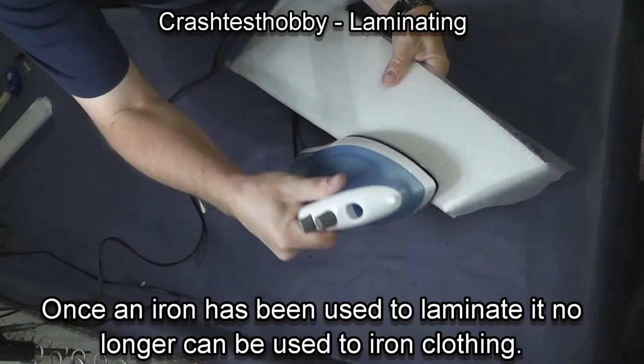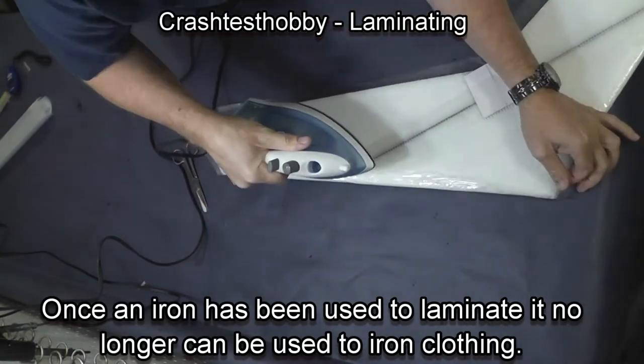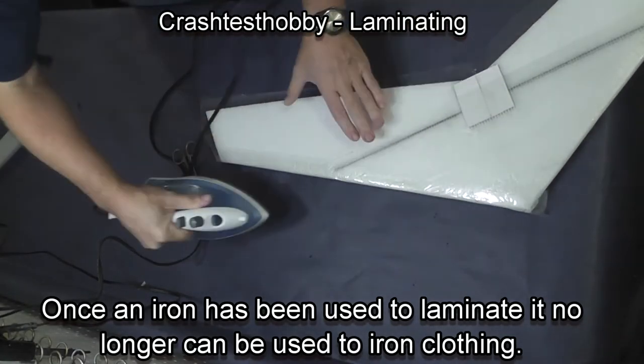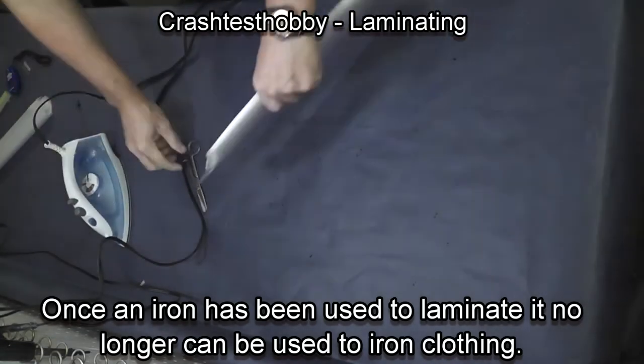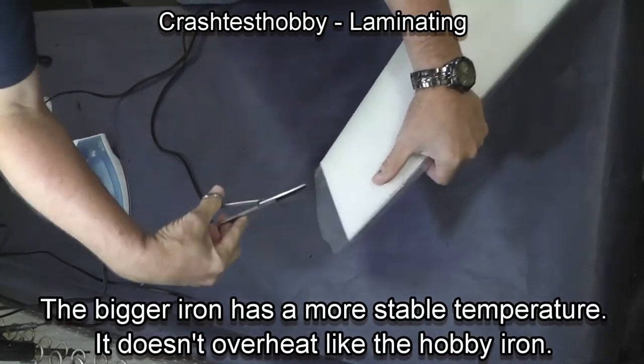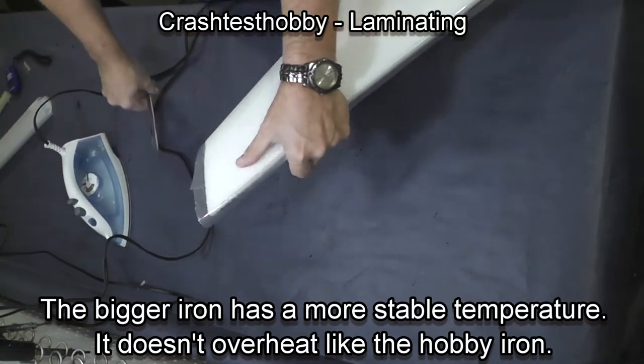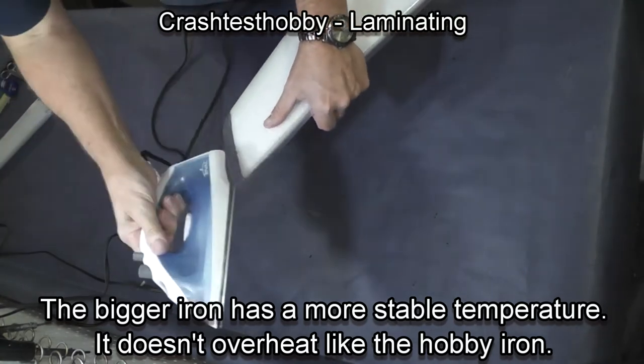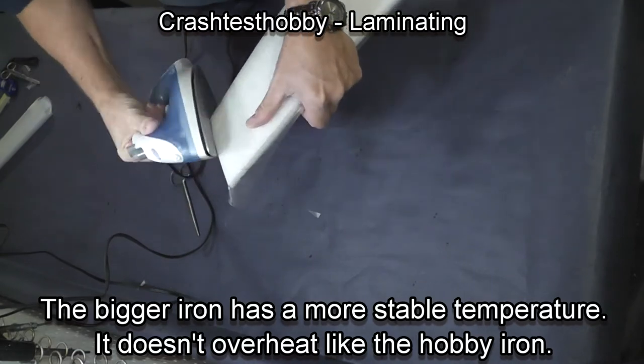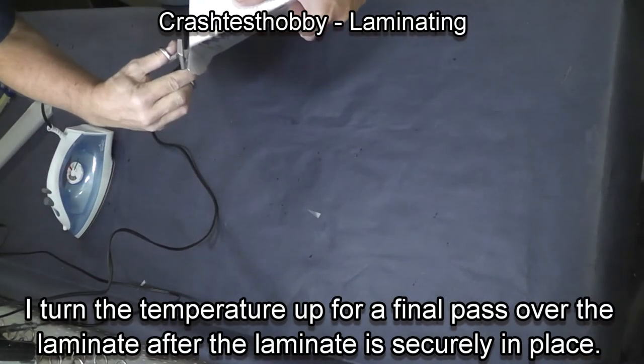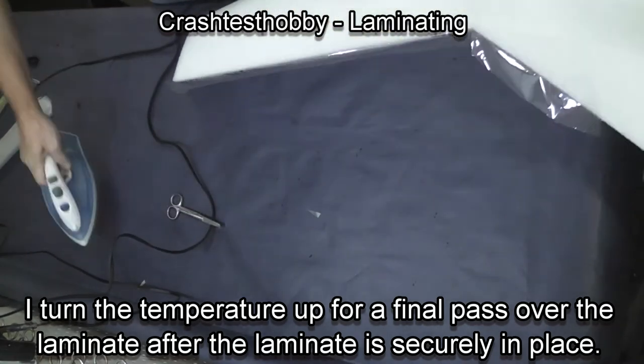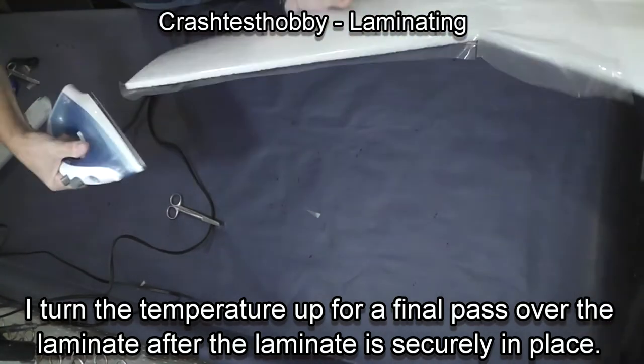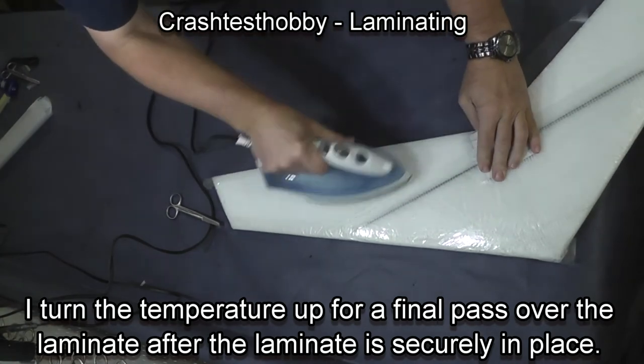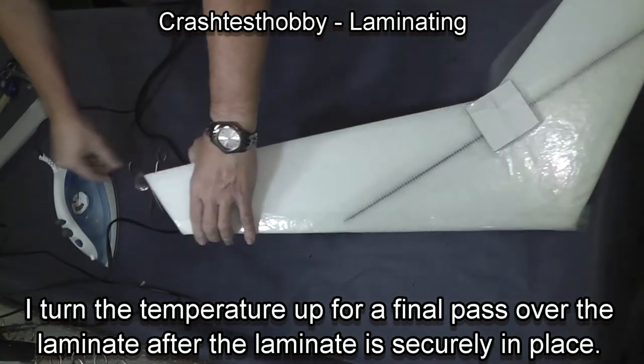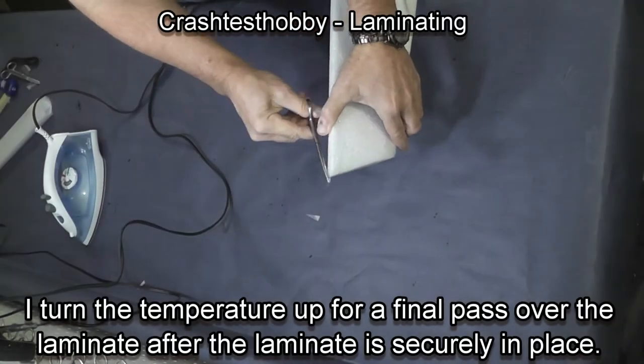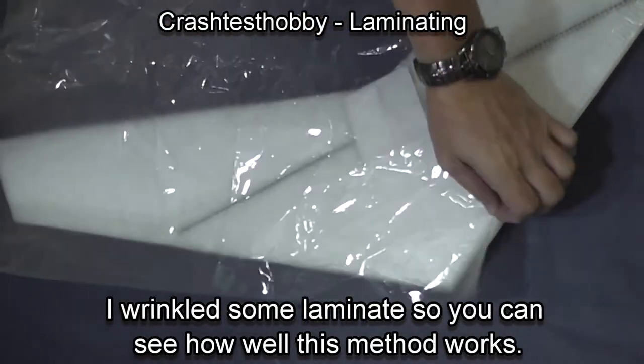First of all is how fast the surface area could be covered. Second of all, this iron only had about a 20 degree variation, while the hobby iron had a 30 to 40 degree variation, which made it easier to maintain the proper temperature for laminating. I didn't have to cool this iron at all, and also it heats up within a few seconds while the other iron takes a few minutes to get to full temperature. As you can see, that's a good comparison of the small iron to the big iron. Big iron actually has me sold for this kind of job.